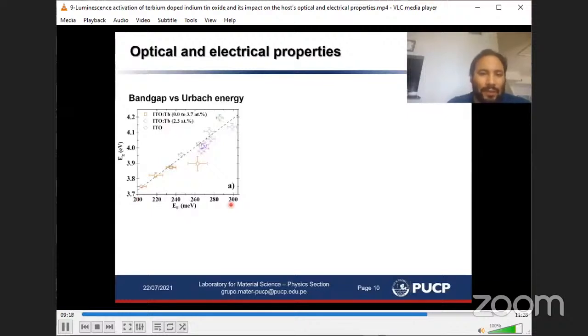We believe that this relation is associated with the fact that when we introduce terbium ions, for instance, or when we perform annealing treatments on the sample, we activate charge defects like oxygen vacancies, among others. And therefore, we increase the optical bandgap by means of the Burstein-Moss shift. So when we activate these charge defects, or form new defects by annealing treatments or the inclusion of terbium ions in the host, we are also increasing the Urbach energy of the system.